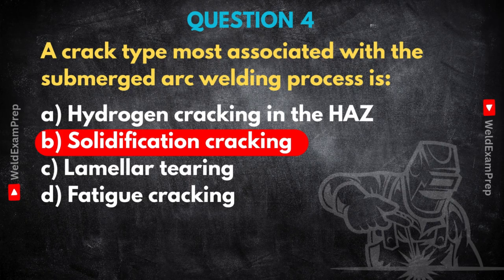Absolutely, 100%. Recognizing those associations, process to defect links, that's a hallmark of a good inspector. If you know it's SAW, your radar for solidification cracking should immediately go way up. You'd focus your visual checks and maybe NDT, like dye penetrant or magnetic particle, specifically looking for those telltale signs. Often they appear as cracks right down the center line of the weld bead. Right in the middle. Yeah. Knowing the process helps you anticipate the likely problems, allows for better prevention during welding, and more targeted, effective inspection afterwards. Makes total sense.